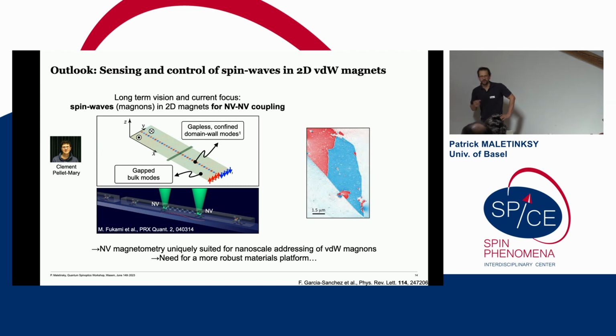Good, so this is the vision, and I want to stress once more that I think NVs are quite uniquely positioned to address spin waves in van der Waals materials, because pretty much no other technique, to my knowledge, has the required sensitivity and bandwidth for that. But in order to go in this direction, we need better materials. This material here, chromium triiodide, I mentioned it already before, is really very finicky, it's very brittle, it exfoliates in very small flakes, and it has a very short lifetime. There's a lot of reasons why it's very difficult to work with that.